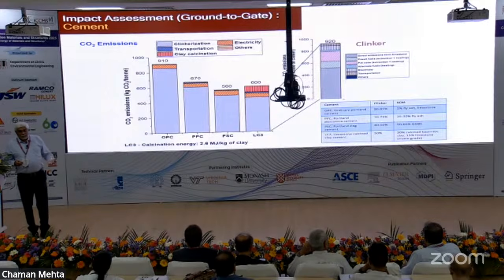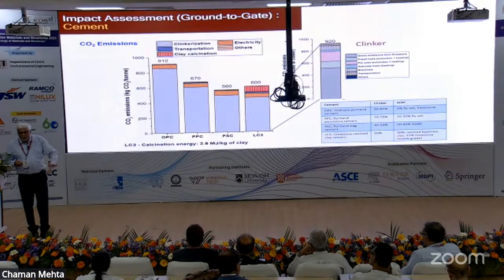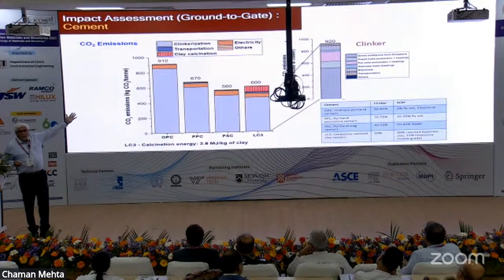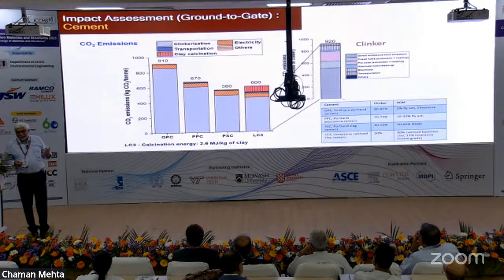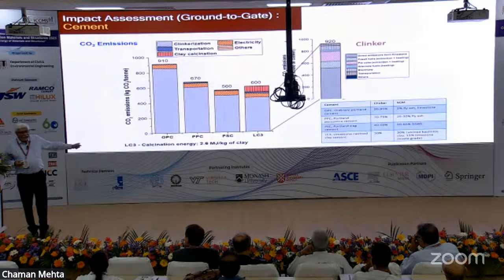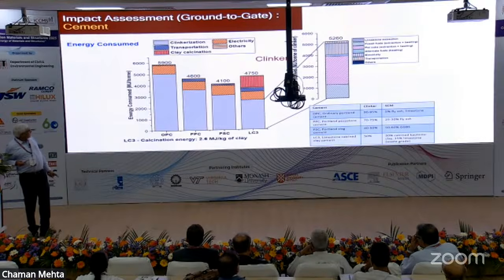Carbon footprint. We talk a lot about carbon footprint. There's hardly any data in India, Indian conditions. So we started going to cement companies, getting the data directly from plants, and you can see the benefit in Indian conditions of using blended cement. You bring it down from 900 kg of CO2 to about 500, 600 kg. So huge benefit. Without changing any other property. The cement complies with the standard, but it has a lower carbon footprint.